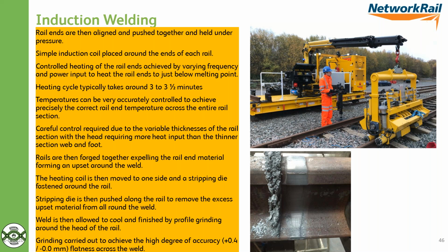The uncut ends, any oxidation or anything else, is then extruded out the outside, and the rail, much as a thermic weld is stripped, or a flash butt weld is stripped in virtually the same way. But some big advantages with it: you're able to much better control the heat input. And effectively, it's like switching on your cooker. You dial in the numbers you want and the time. You can hold the temperature. You can use that quite effectively. It's quite quick, and it uses a vastly lower power than you would require for a flash butt welder.